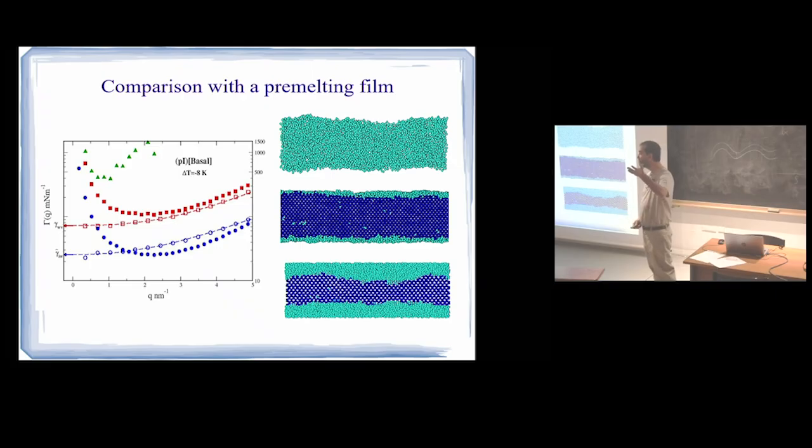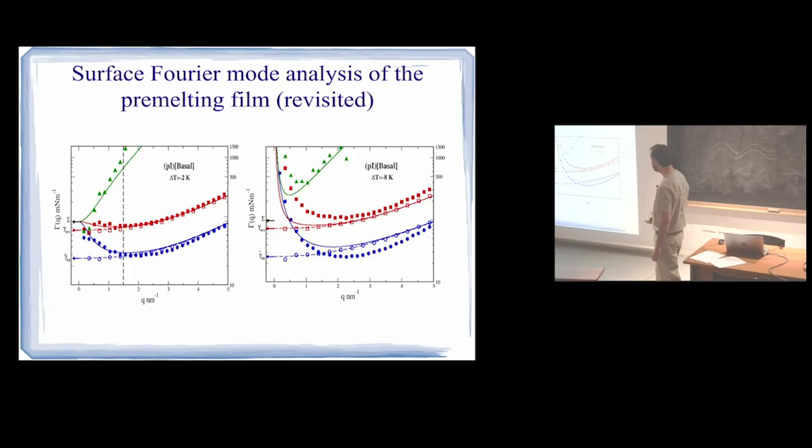Okay, so here I have a roughening transition. At high temperature, my prism face was rough. At low temperature, it looks smooth. So I do have the roughening transition in the prism face of ice. I've shown that. And in fact, if I take the results at -2 and at -8, these simulation results can be roughly well fitted by my model. At -2, they were very well fitted, and at -8, they are not quantitatively fitted, but qualitatively they do get the fit. So this seems to confirm the theory.